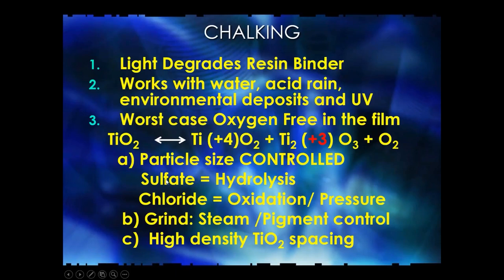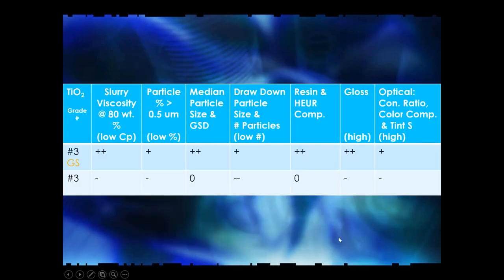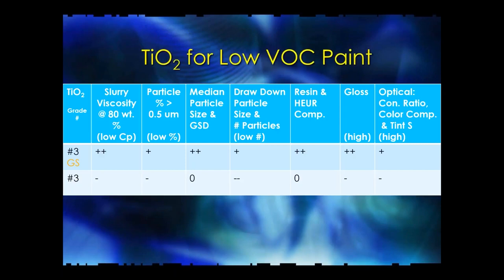There are two processes. One is sulfate, which is using sulfuric acid by hydrolysis process. The other is chloride, which uses oxidation, for which I got a very nice patent for making particle size. There is, in the process of making the titanium dioxide, steam energy. Now, somebody asked the question, do you jet mill the product? And the answer is all commercial product is jet milled. Almost all of it is steam ground, and there are additives that are added to the steam that act as steam dispersants that help break up the titanium dioxide during the steam grinding process. For high density applications in paint, you want to have some TiO2 spacing. And fortunately, the coatings they put down on the surface help you in keeping the TiO2 spaced.